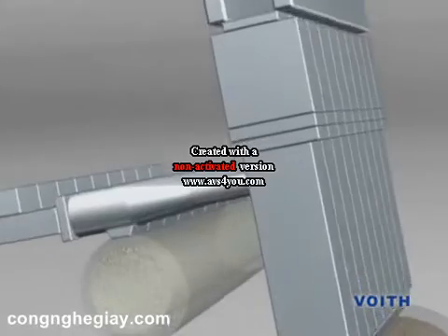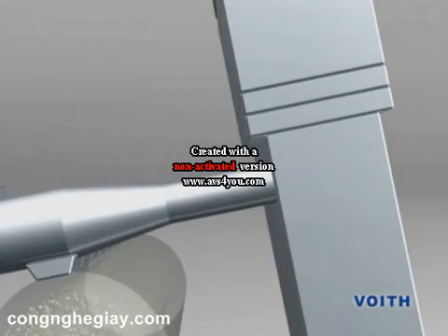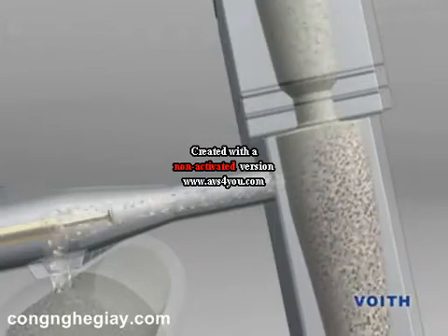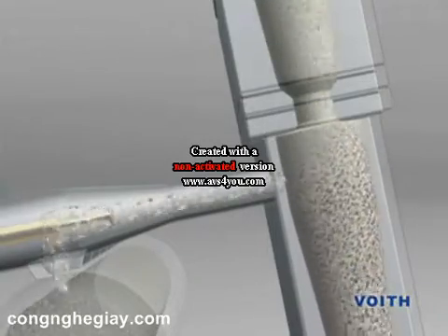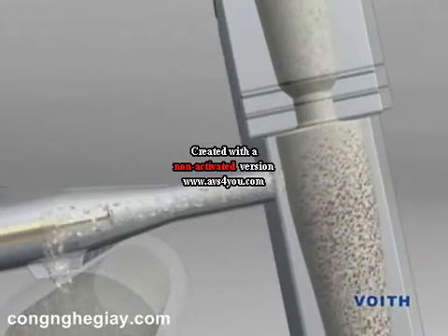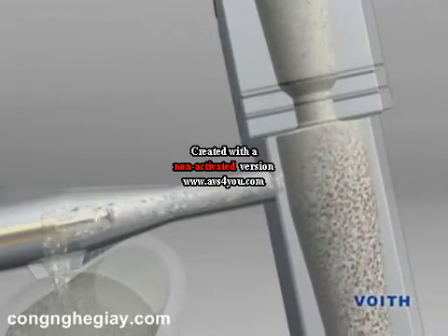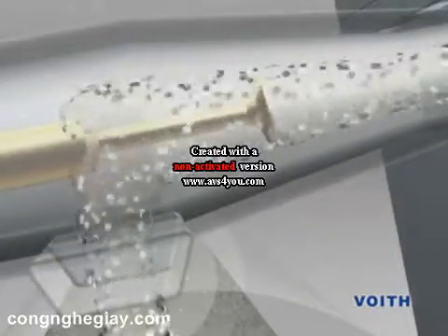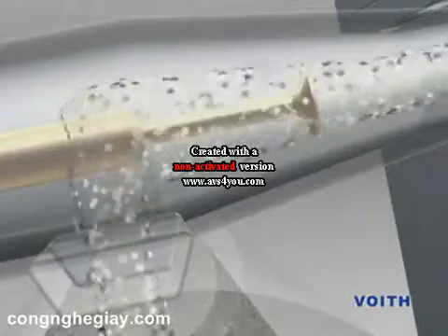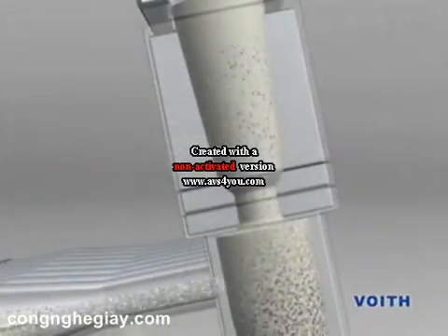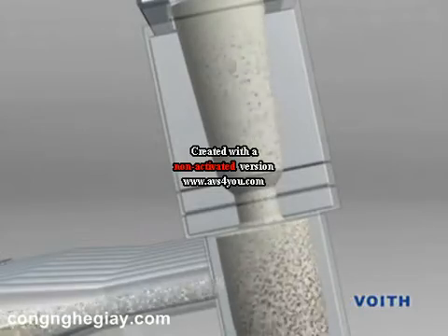In the two headers, the main flow and the dilution flow are distributed at constant pressure across the machine width. In the mixing chambers, the main flow is mixed with the dilution flow. The module jet units with the mixing chambers and valves are arranged beside each other over the entire width of the head box and have the function of regulating the local stock consistency. A metering valve controls the exact mixing ratio. This mixing ratio ultimately determines the basis weight of the finished paper.